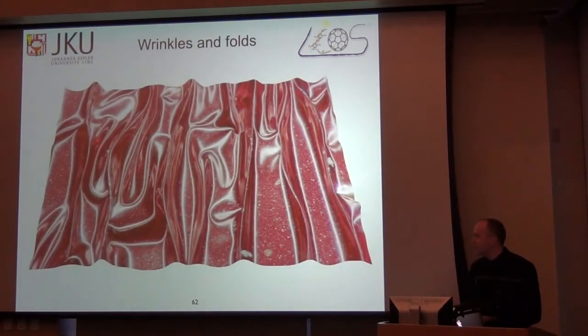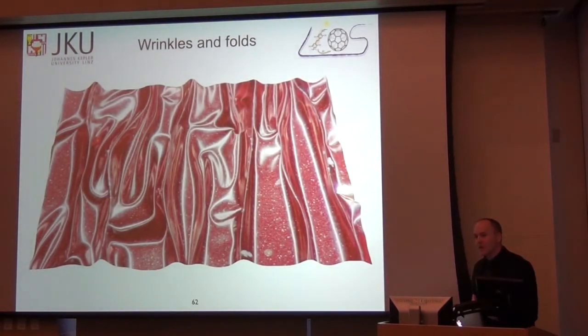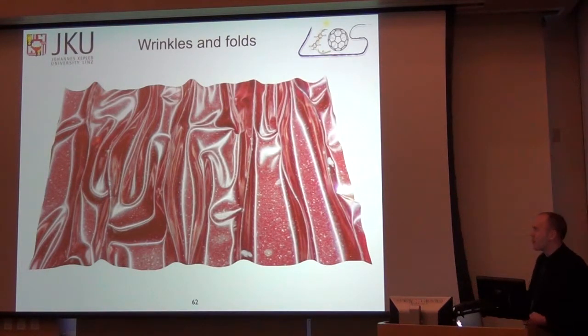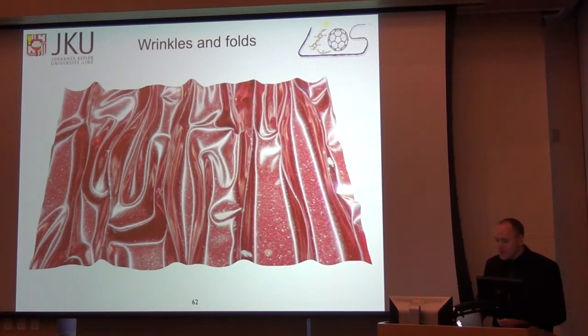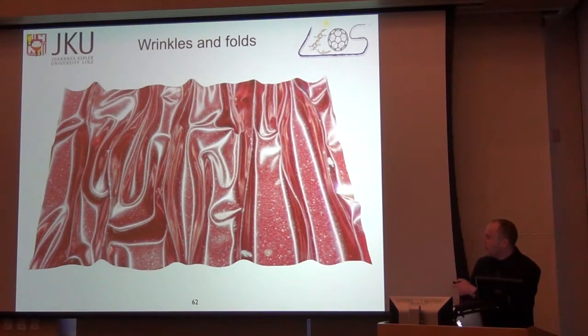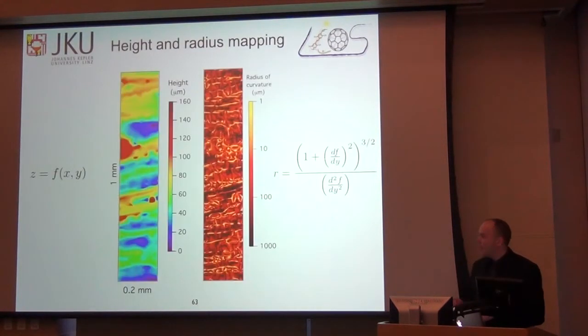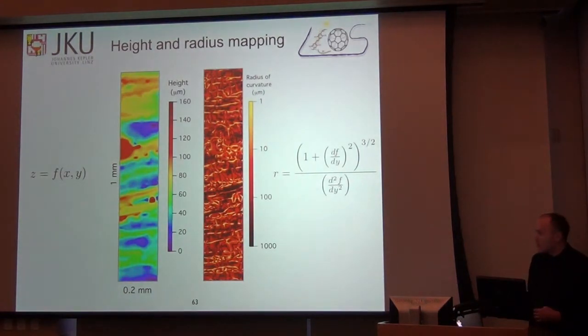So using this deformation technique, we've made a network of wrinkles and folds, but these folds can give us a better idea for what the radius of curvature is that we're subjecting these films to before suffering complete damage. So we take what's called a 3D optical microscope, and you scan the focal plane and measure the height of the focus of each point, and you get a height map of the film over a large area.